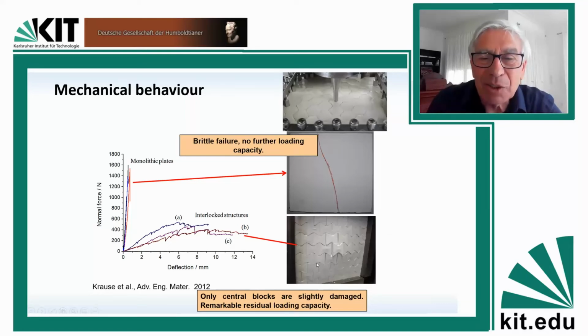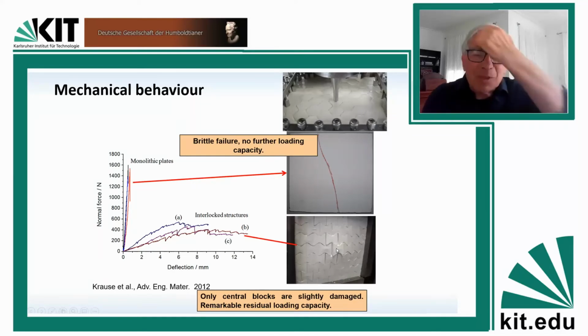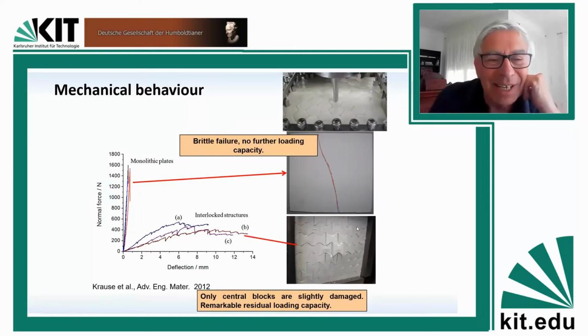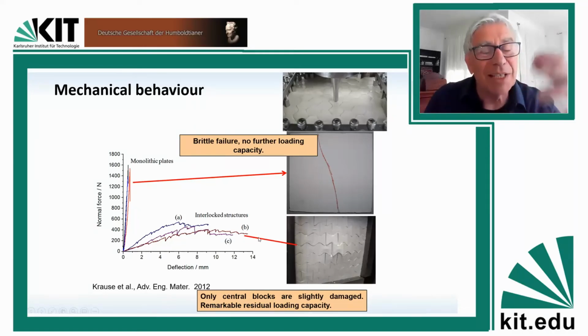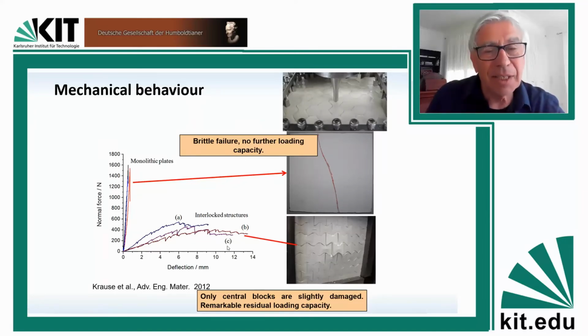You can see it here, actually. The block to which the load was applied has moved quite a lot, almost by half of its thickness, and yet it is still within the structure. It is arrested by its neighbors. The load-bearing capability dropped, but the entire work done, the entire energy that such a structure is capable of absorbing, that is the area below this curve, is obviously much larger than in this case. So these are structures which can absorb energy.